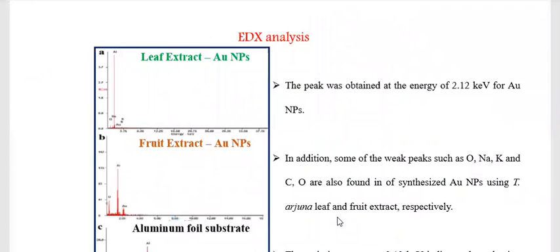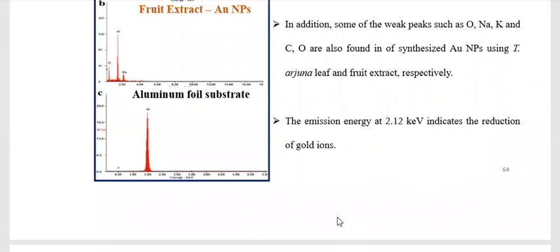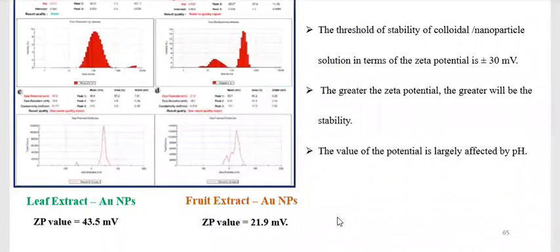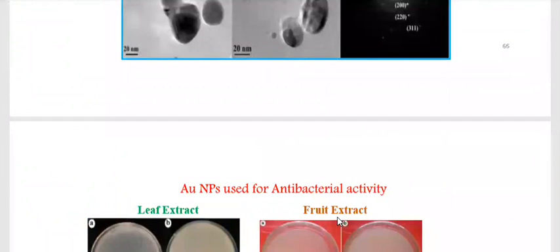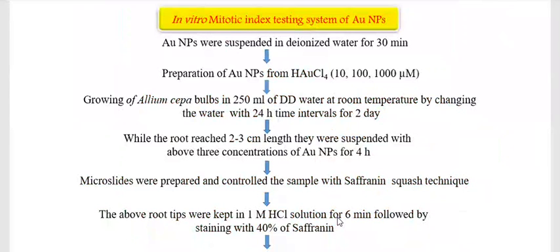The gold nanoparticles were divided into 10, 100 and 1000 micromolar. Allium root samples were soaked for 24 hours at intervals of 2 days. The 2 to 3 centimeter roots were suspended with the nanoparticle for 4 hours. Microslides were prepared with control samples, and squash technique was used. The 1 molar HCl solution was used with 40% safranin. Finally, you observe under confocal microscopy. The cell division was evaluated, and the mitotic cell division gradually increases with the concentration.